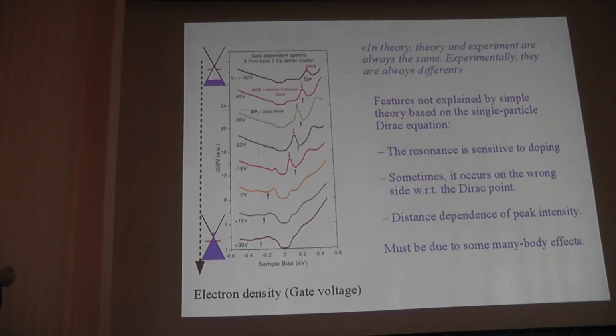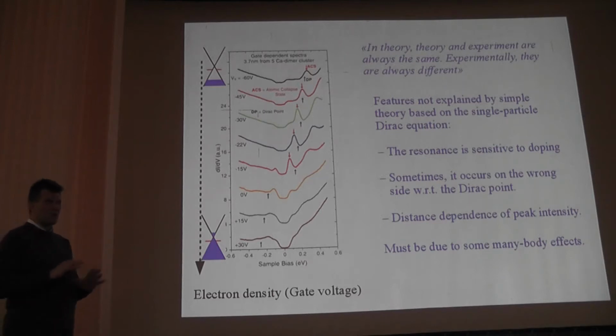Let's start with deep hole doping. So then the Dirac point is here, and the atomic Coulomb peak is seen at an energy above the Dirac point. Well, the theory predicted that it should always be below this point, because basically it's an electron level dived into the hole continuum. So it's slightly above, but never mind. Let's keep going. As we change the doping from deep hole doping to neutral to positive electron, you can notice that the peak loses intensity and eventually simply disappears. So one of your tasks here is to understand the doping dependence.